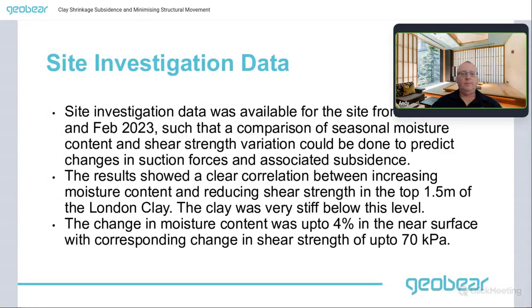Site investigation was available from October 2020 and Feb 2023, such that a comparison could be made of the seasonal moisture content and the shear strength variations to predict the change in suction forces and associated subsidence. The results showed a clear correlation between increasing moisture content and reducing shear strength in the top 1.5 meters. So as the soil dries out, it gets stiffer. As the soil gets wet, it gets softer.